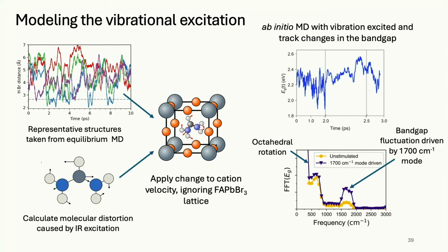Another proof that this is true is that we took this molecule, and in our theoretical simulations, we induced the vibration. We moved the carbon to the side, so then it's going to oscillate back and forth. And then we saw the band gap oscillates. If you Fourier transform this, wouldn't you know, the frequency of 1700 wave numbers is where the band gap oscillations happen. So this is showing that in our simulations, the vibration of the molecule is directly talking to the band gap.